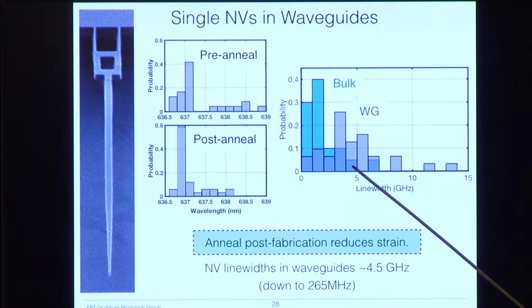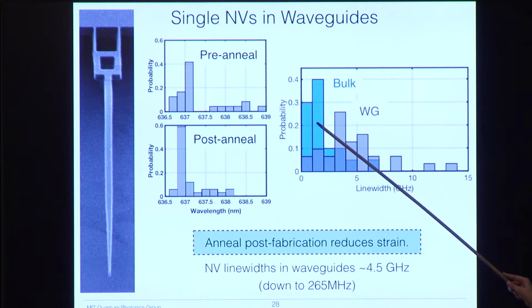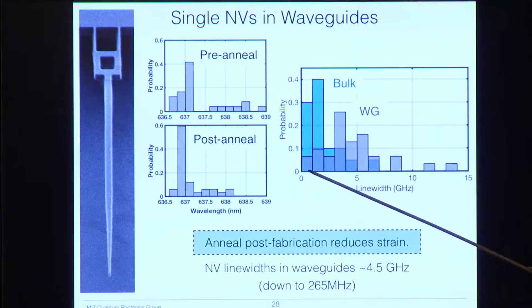Second, we look at the line widths, and we look at the line widths in bulk, so that's these blue, as well as in waveguides. And we can see, while we do get some low line width NV centers in waveguides, definitely the distribution has shifted towards larger line widths. So although we can get down to 265 megahertz, which is still kind of 20 times higher than they should be, we see that there is this increase in line